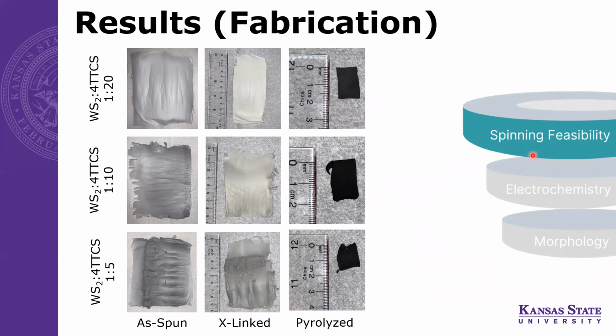From the increased mass loading of WS2 in the WS2;4TTCS solution, it was apparent that the fiber mat looked darker than before, with a similar weight retention after cross-linking and pyrolysis steps. The visual inspection clearly tells us that more of the reinforcement material might be present in the final fiber mat form after cross-linking and pyrolysis.